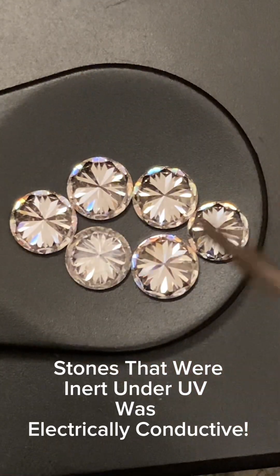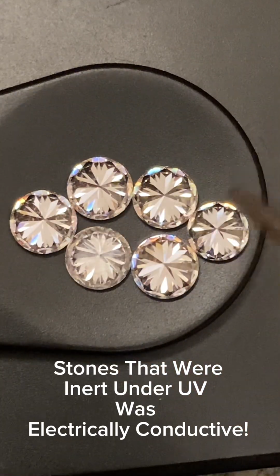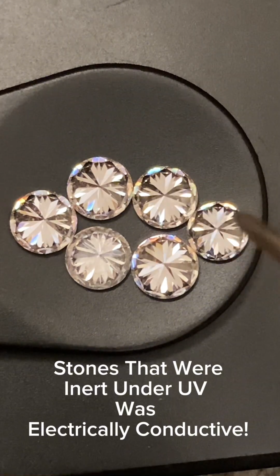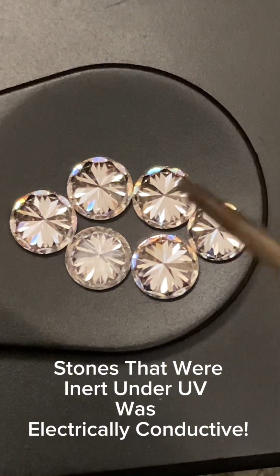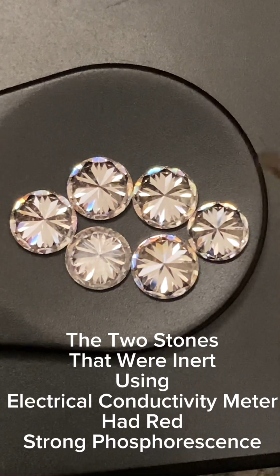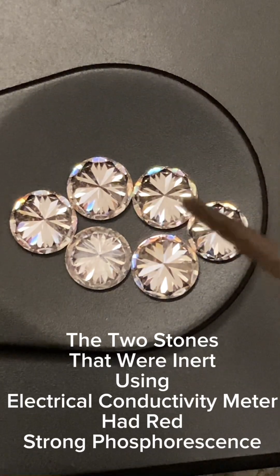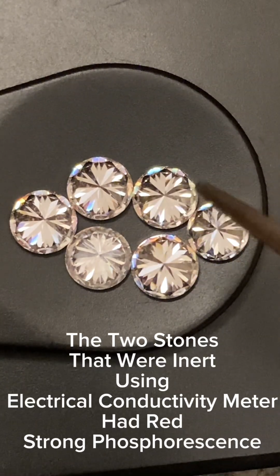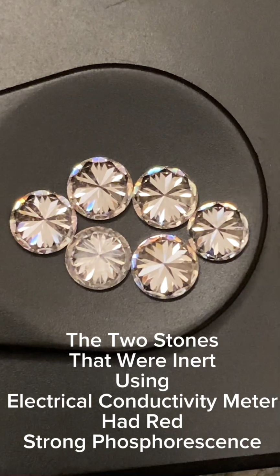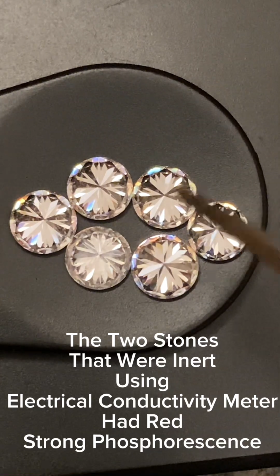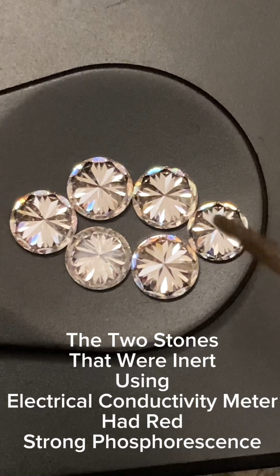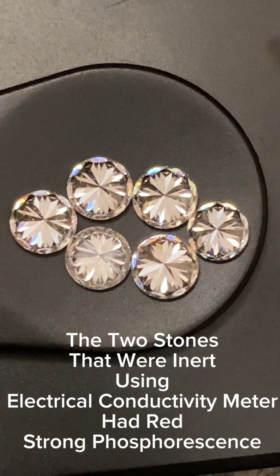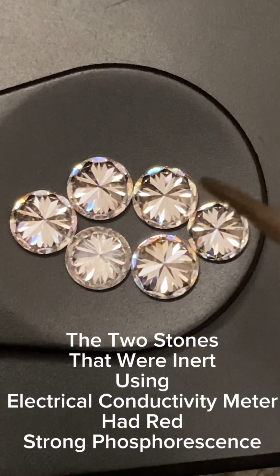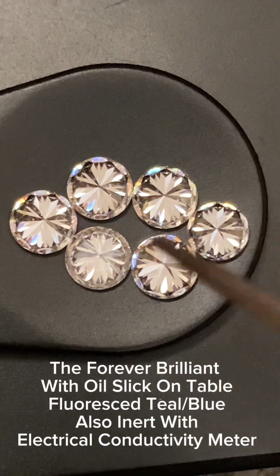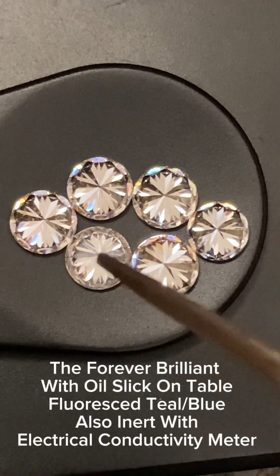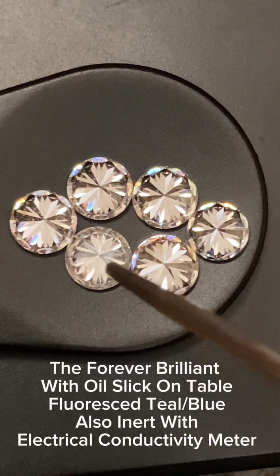We had two stones that were completely inert under the conductometer and did not give us a Moissanite reading or electrical conductivity reading. And these are the two stones that phosphoresce red. So it's indicating that there is some type of surface coating, most likely polycrystalline diamond by the chemical vapor deposition method. And this stone, we can clearly see that there is some type of surface coating.